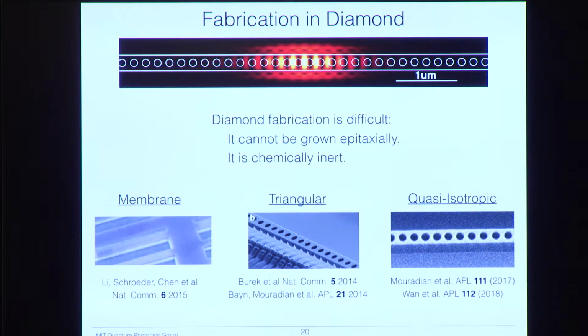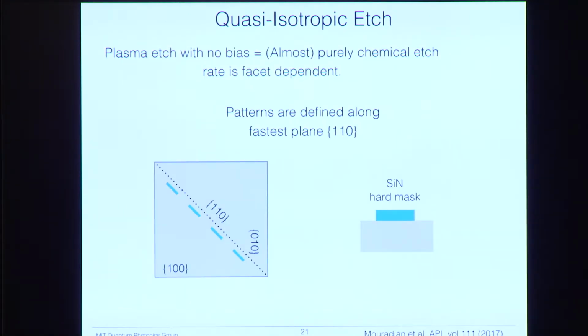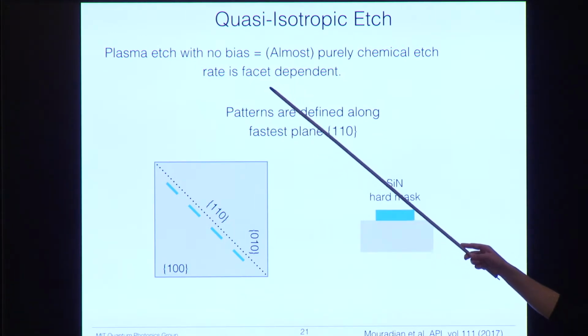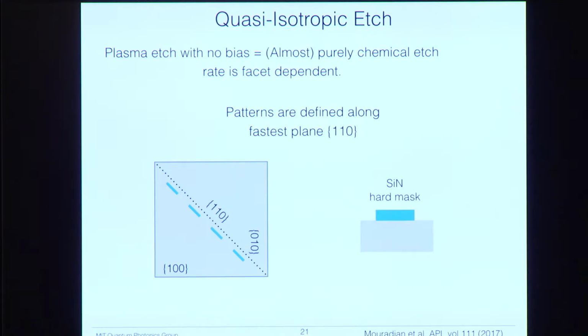And so the way that we worked to make optically isolated nanostructures from bulk diamond is with what we call a quasi-isotropic etch. So I'll explain that to you now. The main point of this quasi-isotropic etch is that we use a plasma etch, but with no bias. And so that gives us an almost purely chemical etch, and in all directions, and that means that the etch rates are dictated by the etch rates of each plane. So we see that the 110 plane etches fastest. So if we are in a 100 diamond, so that means the top face is 100, we align all our structures along the 110 plane. So that means that this plasma etch etches in much faster than it etches up. And so that's why in the end we'll be able to make these rectangular structures.